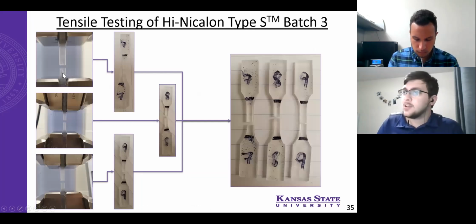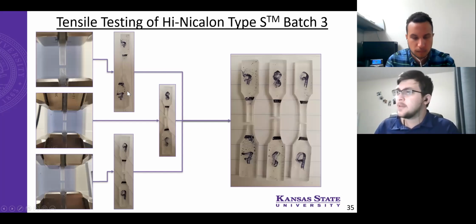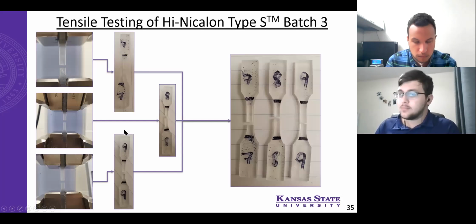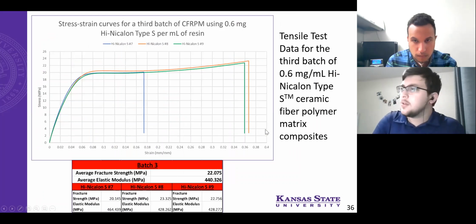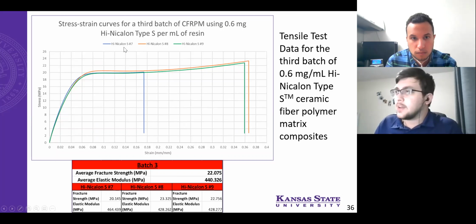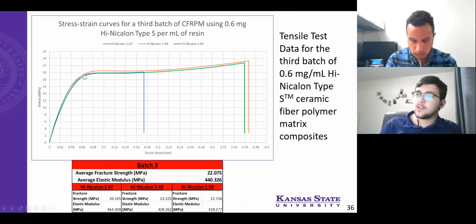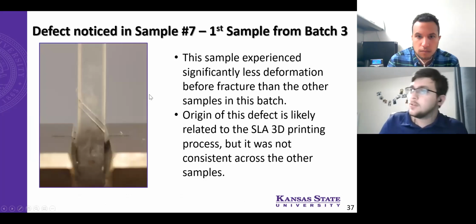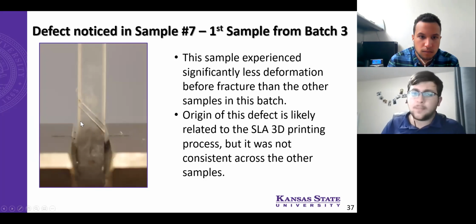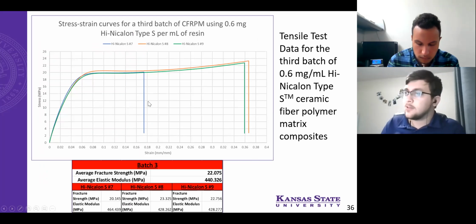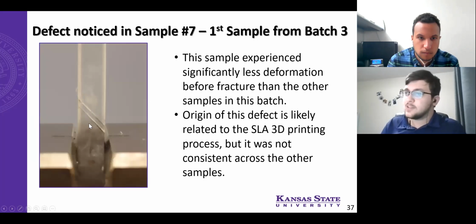Moving on to batch 3, where we used a different tow, but the same type of fiber, the same concentration, more consistent fiber length. During, after, and here we could see the high Nicolon S, or the first sample of this batch, actually broke at half the length of the other ones, and this batch underperformed compared to the other 2 batches in the sense of 464, 428 megapascals for their elastic modulus. I do believe that there was a defect in sample 7, which might explain why it broke here. Because you can see this layer line going on here.